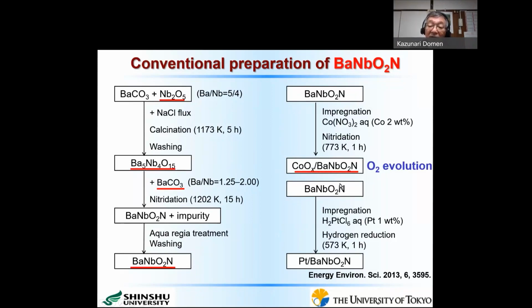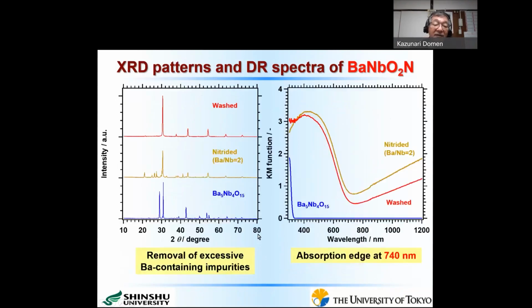And then we also modify this barium niobium oxynitride using platinum. In this case, we use these materials as a hydrogen evolution photocatalyst. And here I show the X-ray pattern, and after washing by removing the impurity phase, we can prepare the single phase of barium niobium oxynitride. And as you see here, this is the absorption edge, located at about 740 nanometer. It is a very long wavelength.